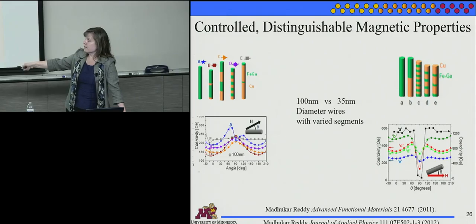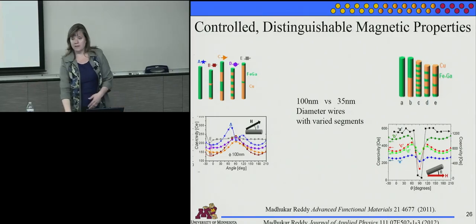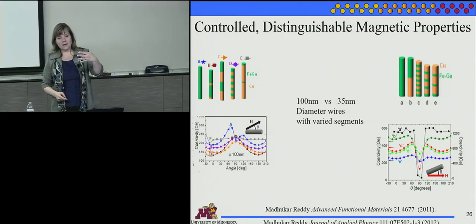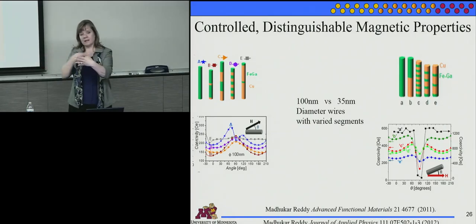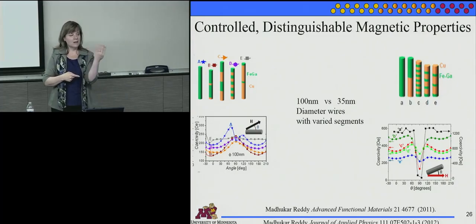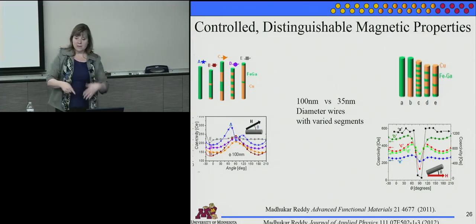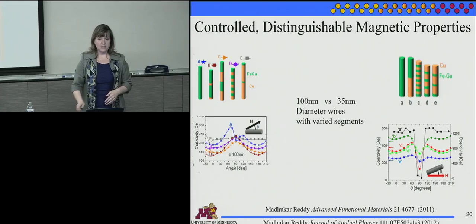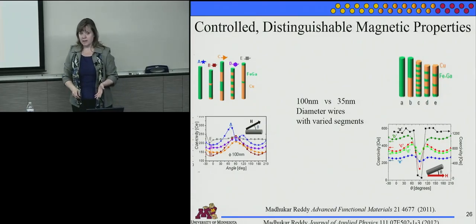This is the coercivity versus angle. So basically, if my field is being applied this way, and then that way, and then left and right, and so on, if my wires are aligned at 0 degree as I'm applying the magnetic field, sweeping the field, or if I rotate this to 90 or to 180, then I'm measuring a different coercivity at all those angles. And that tells you a lot about the switching mechanism of the wires.